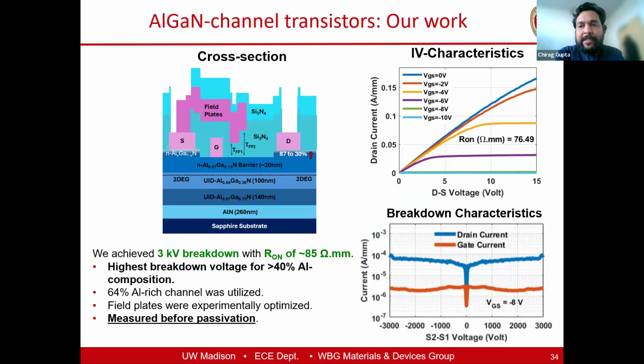And this is again because the conductivity is 10 times lower in these AlGaN channels compared to GaN channels. And one of the key things to note here is that these devices were measured before silicon nitride passivation. So this is right after Schottky gate deposition. We measured it, and we saw somewhere on the lines of 3 kilovolt, but this is without passivation.